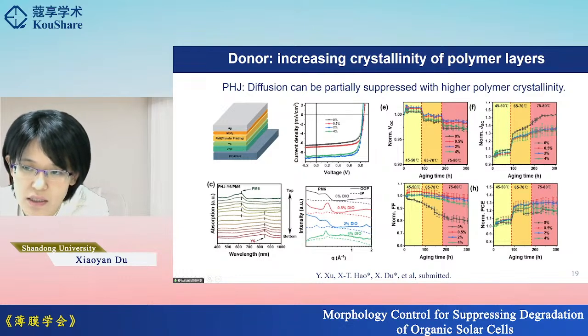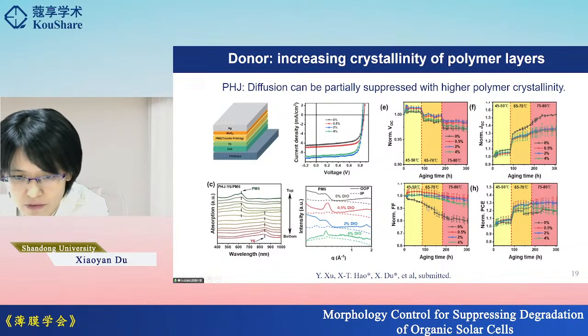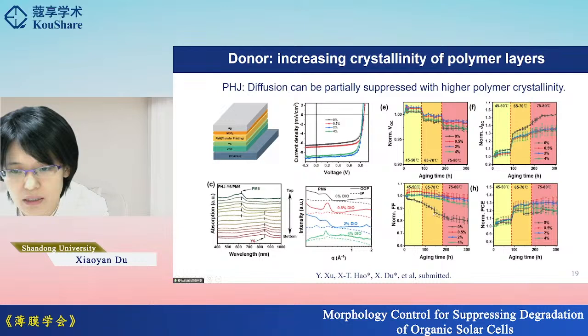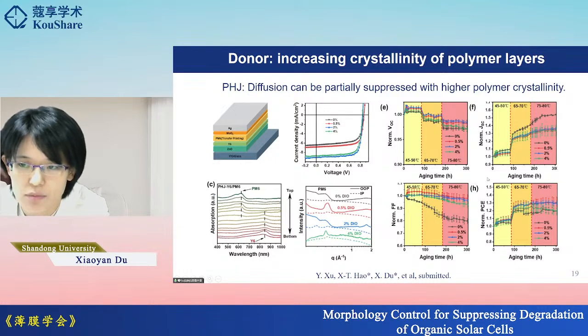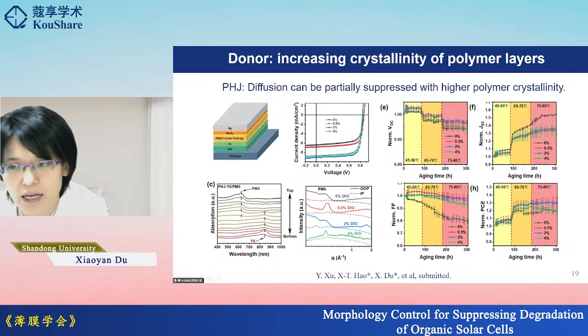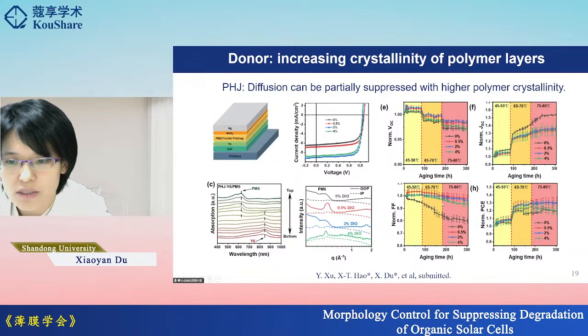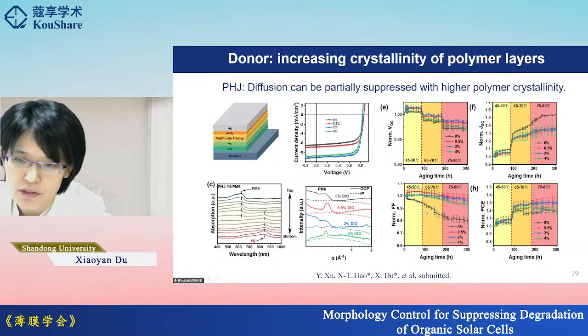The changes in the photocurrent, the VOC, and the fill factor under different annealing temperatures reflect the intermixing of the donor and acceptor at these interfaces. And we see that if we have an amorphous polymer layer, as shown here, the black curve, we see a faster decrease in the device performance, mainly the fill factor, and we see an increase in the photocurrent because we have more intermixing and the acceptor diffusion is more efficient. So this is the result of the device with amorphous polymer layers.